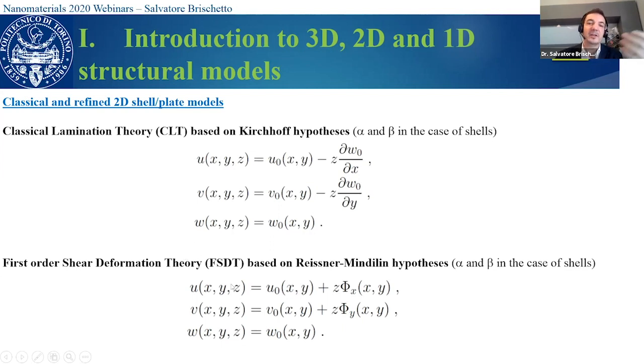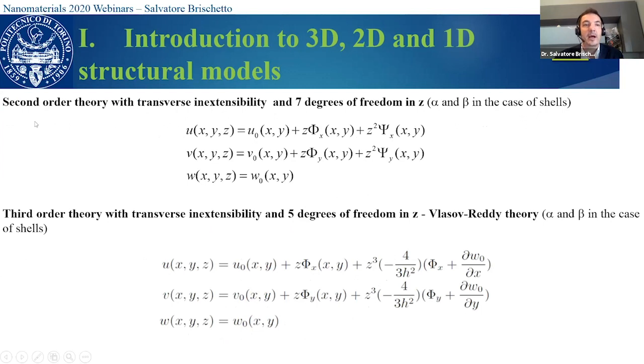A first refinement of this model is, for example, the Reissner-Mindlin hypothesis. This hypothesis, extended to multilayered structures, gives the so-called first-order shear deformation theory. So we introduce the transverse shear strains, and we have 5 degrees of freedom: the 3 displacement components in the middle surface and the 2 rotations. Then we have several refinements of these models. These are some examples. For example, second order theory with the transverse inextensibility, so we have 7 degrees of freedom, or the well-known Vlasov-Reddy theory, where we have a cubic term in U and V, and we have only 5 degrees of freedom, okay?